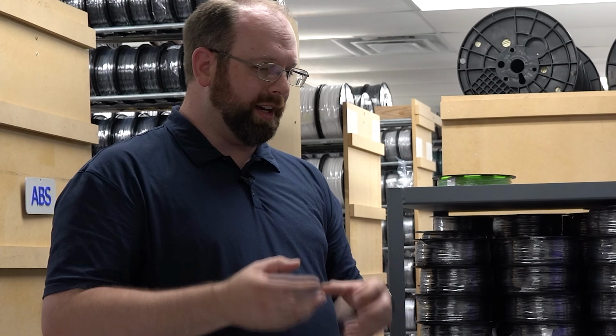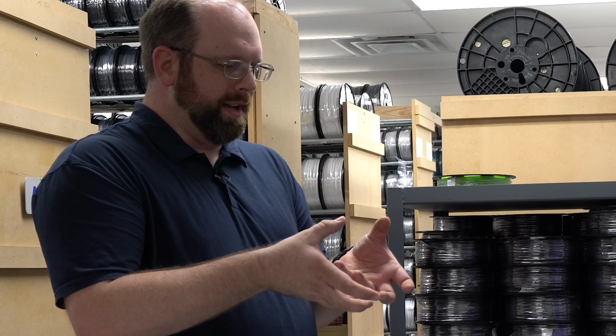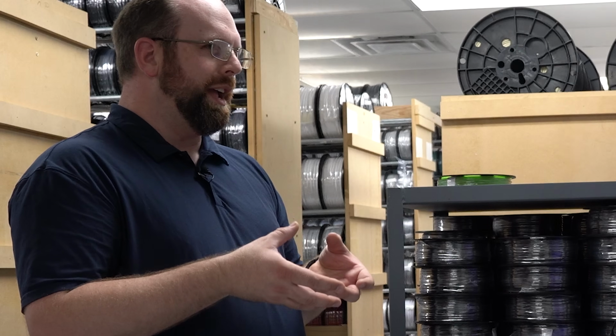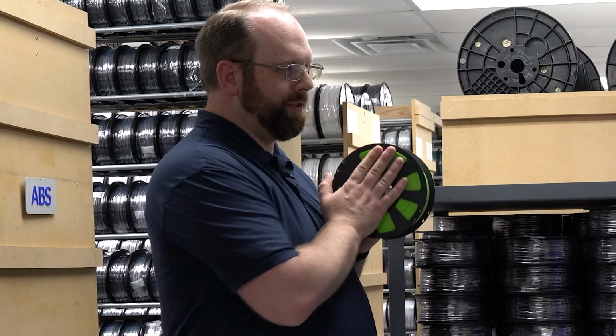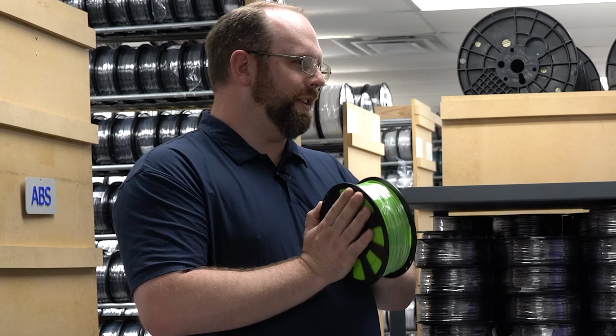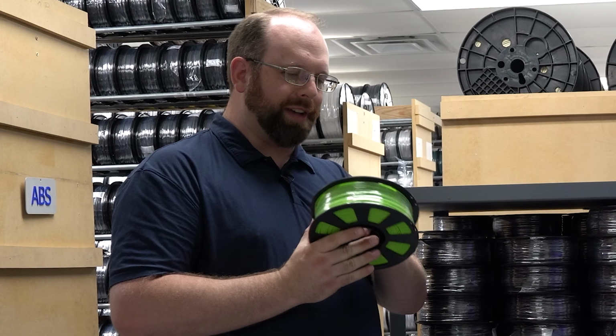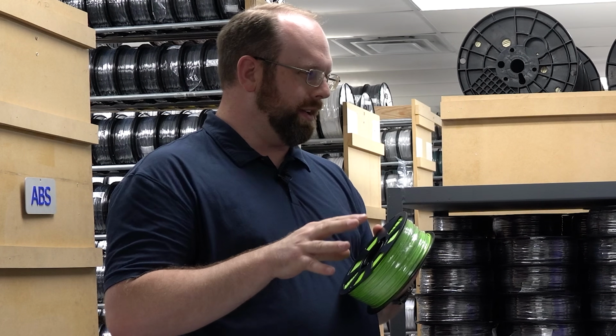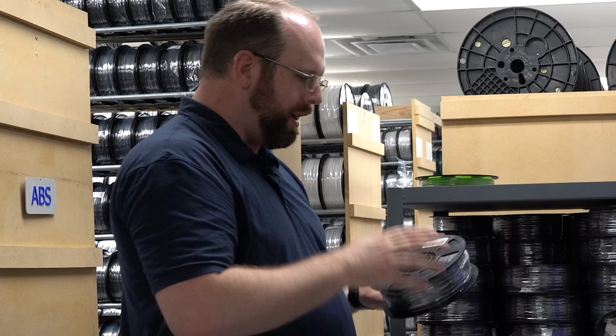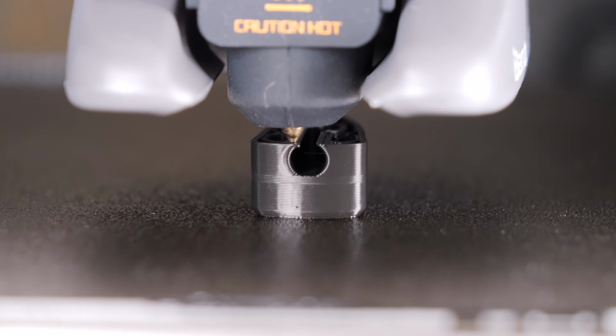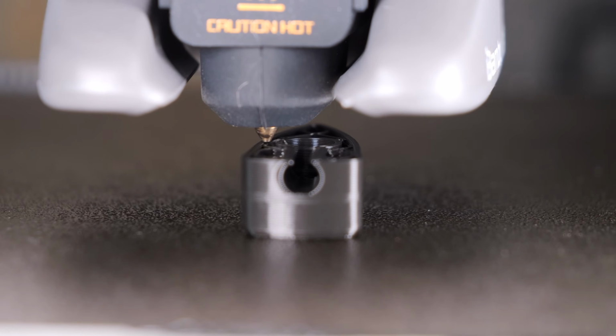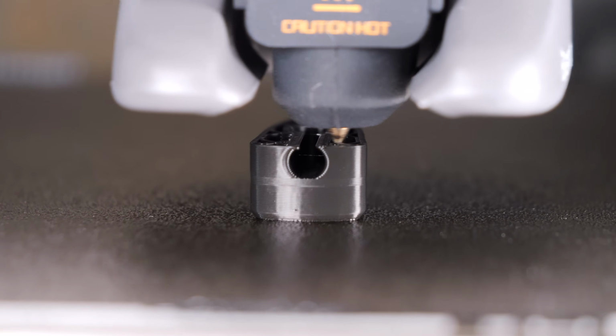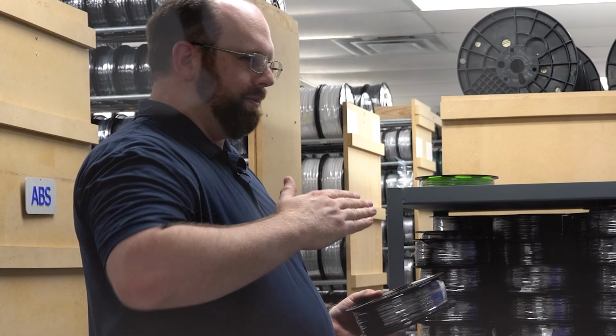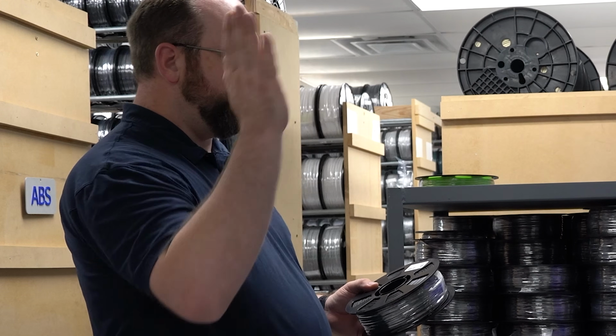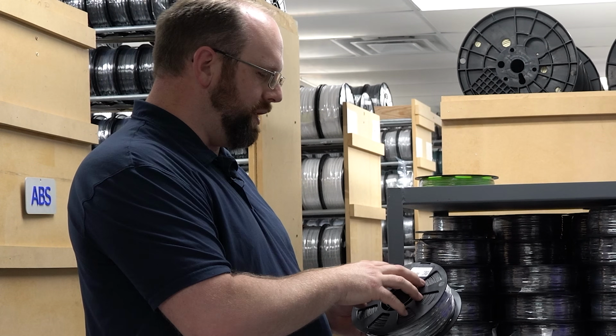It might even be a cardboard spool. Well, it'll soak it up. They vac seal it, and then they send it to the customer. And once it's in there, the moisture doesn't necessarily matter for something like this. Believe it or not, there's a little moisture in here, and I don't know that it would drastically affect your printing. It might minorly. It might a little more on PETG, but there are some good videos online showing that it's not necessarily a 50% increase in performance. It's more like 2 or 3%, and it mainly affects PETG's clarity.